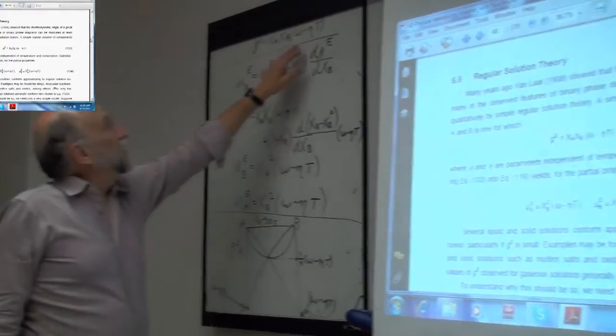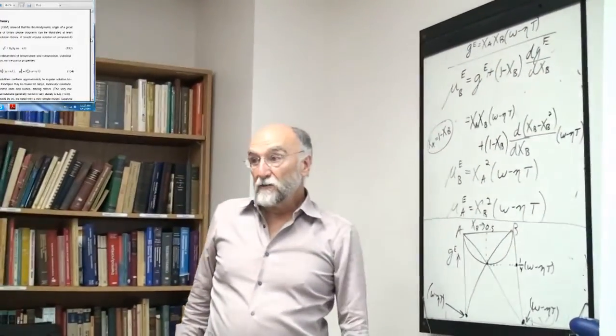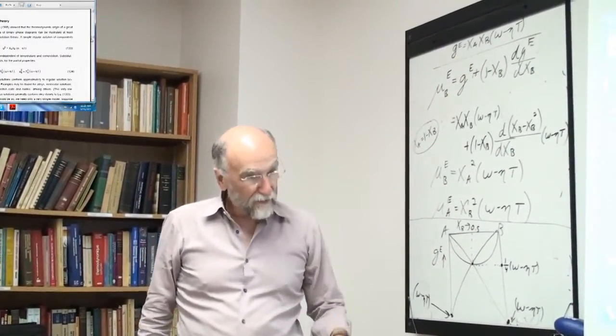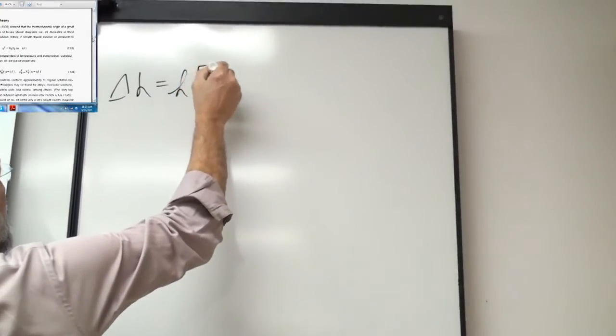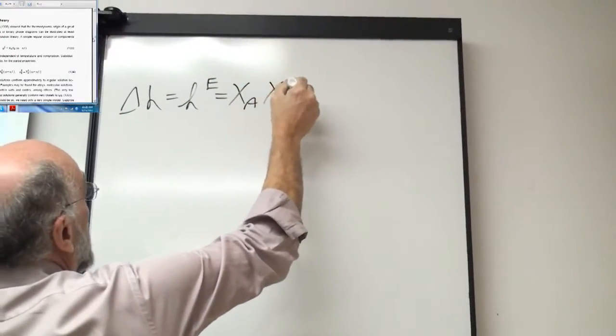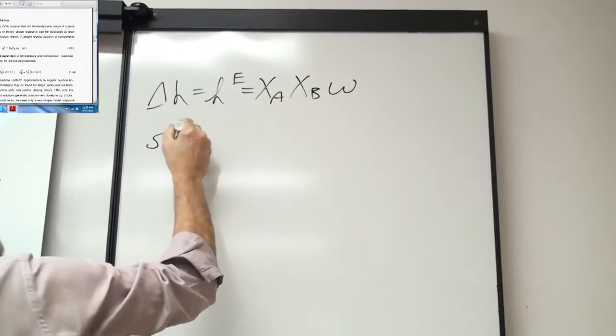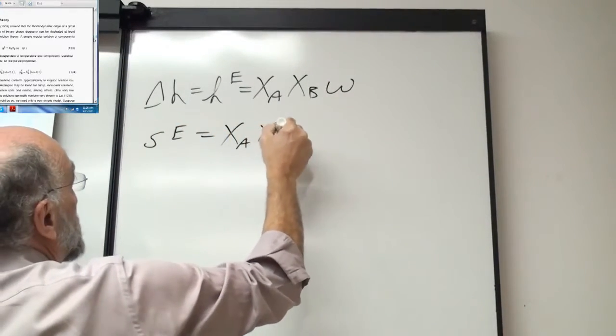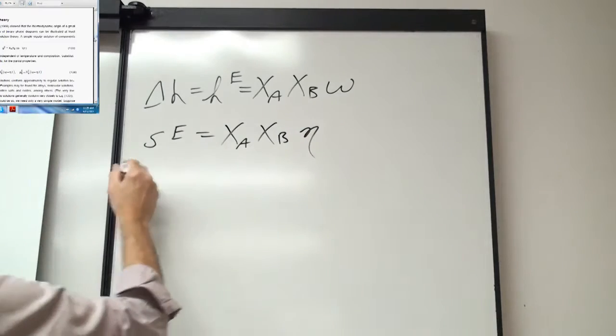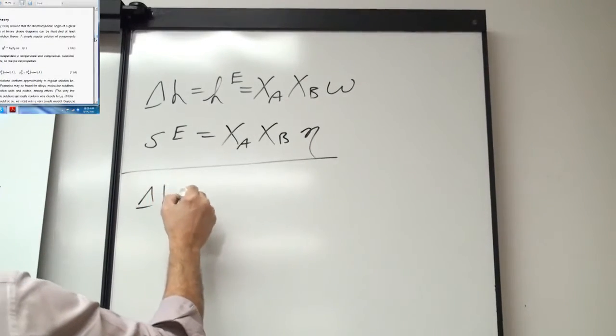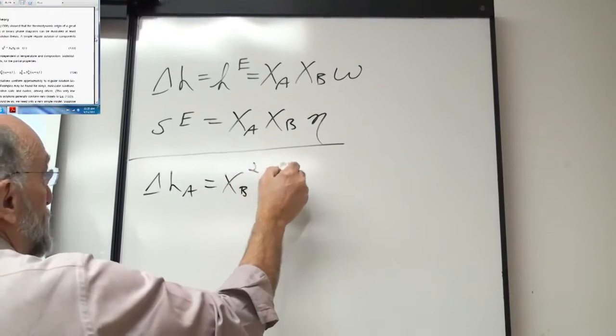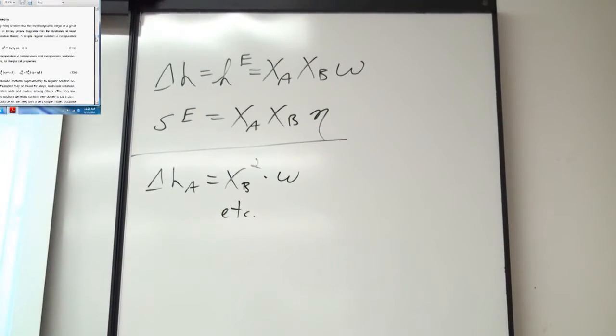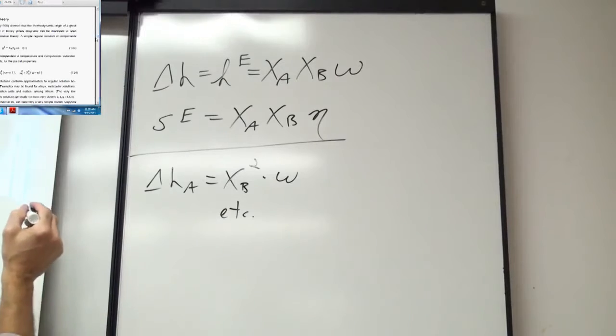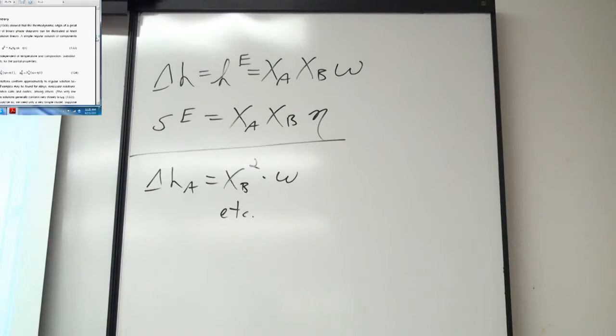Clearly then the omega is the enthalpy term and the eta is the entropy term. Okay, so maybe, if it doesn't bother Virginia, I'll write it over here. I'll say then the excess enthalpy is equal to xa xb times omega, and the excess entropy is equal to xa xb times eta. Clearly your partial heat of A is xb squared times omega, etc. And of course the mu excesses that I wrote over here, well, I can write that over here.